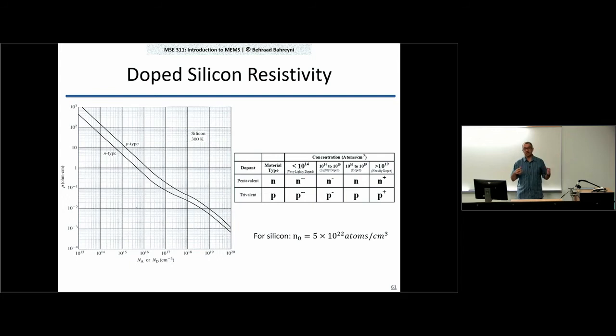Now the question is, how can we do that? How can we just add 1 part in a million of phosphorus to a silicon crystal in order to get the resistivity that we want? And then for the sake of comparison, remember that the electrical resistivity for aluminum, for example, is about 2 microohm centimeter. For silicon, you don't really get to that level, even if you dope it to about 10 to the 20 dopant atoms per cubic centimeter, right? So you're still far from metals, but you're getting close.